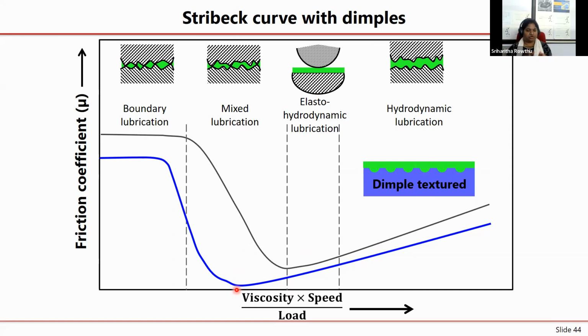First of all, you need relatively big areas of patterned surfaces. It's not that 5 by 5 micron or 100 by 100 micron is going to be sufficient. Your stroke itself is 4 mm. That means my counter body is going to move 4 mm totally in this direction. So your 4 mm, and then the thickness is going to be the diameter of your counter body. So it's actually a macroscopic area we need to texture.